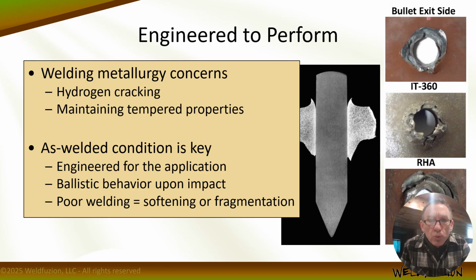So heat input is absolutely critical, right? Our goal is to maintain the balance of martensite without embrittlement and maintain the ductility without overheating or over-tempering, which would actually soften the material. So it's a balancing act. Here, the as-welded condition is key, right? These materials have been engineered for specific applications and predictable behavior upon impact. Welding practices need to preserve those mechanical properties, and that's why we need to use qualified welding procedures that have been tested and qualified personnel that have demonstrated they can exhibit the techniques and perform the techniques required to achieve the desired weld properties, right? So it goes hand in hand. It's not rocket science, but it is weld science. Poor welding can lead to softening or embrittlement, which won't provide the desired level of protection, which could place lives at risk. So this is mission critical stuff.